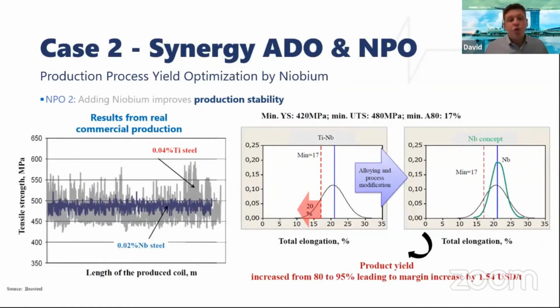And these two used to have a 20% rejection rate due to low elongation. And after the change for niobium, that was reduced to 5% total, considering all different types of quality issues. And even the niobium concept, with the alloy cost being slightly higher than the titanium cost, the overall cost was reduced by $1.54 per ton. This is a great example on how alloy design optimization and process design optimization can have a synergy to bring improved cost by production yield or process stability.